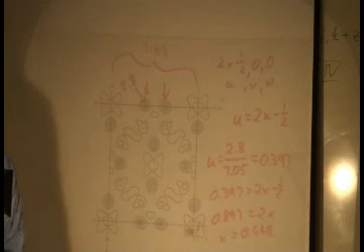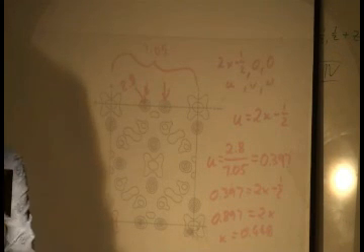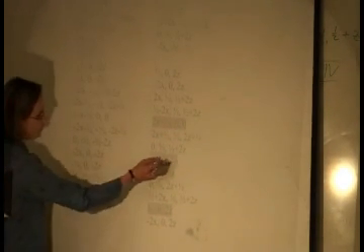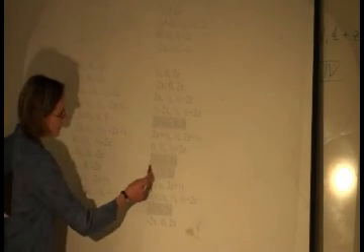So let's look back at what kind of interatomic distances we have that involve z. Well, there are some that involve x also. So they make our life difficult, right? Because we first have to figure out where the heck we actually are. And conveniently, there are some that only involve z. Do we like those? So 1/2, 0, 2z would be a good one to use.